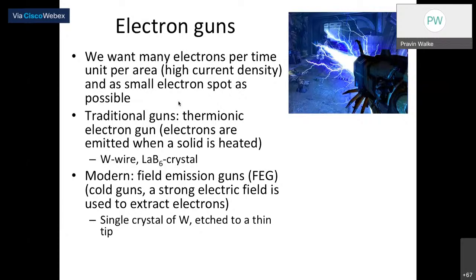There are various guns people are using in different systems. The traditional gun is the thermionic electron gun, where electrons are emitted when a solid is heated. For example, here tungsten wires or lanthanum hexaboride crystals are used, right? In modern days, people are using the field emission gun, called the FEG. That is a relatively cold gun, but it needs a very strong electric field to extract the electrons, right? In this kind of field emission gun, usually a single crystal of tungsten is used. The tungsten is made into a very thin tip, so the emission will be very sharp.